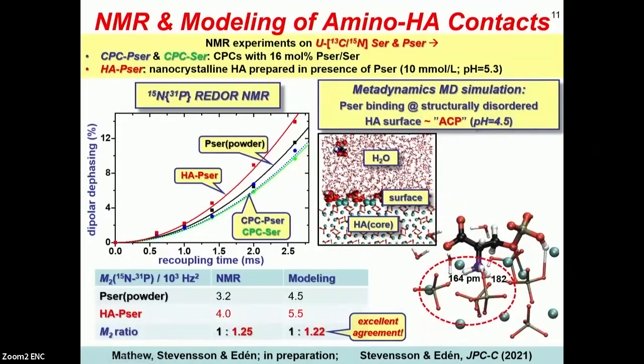So we will next take a look at the potential binding of the amino group at the structurally disordered calcium phosphate surface. Besides the two cements, we used the isotopically enriched phosphoserine for preparing a model system of nanocrystalline hydroxyapatite that was grown from a solution comprising phosphoserine. We refer to this system as HA-Pser, and it's also an approximant of the ACP component of the cements, because all nanocrystalline apatite particles are coated by an amorphous surface layer of ACP.